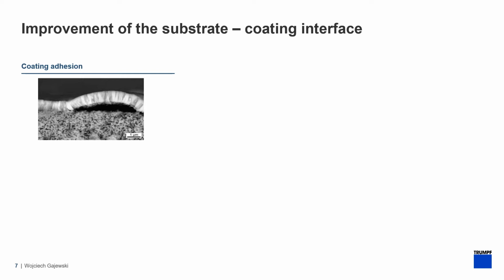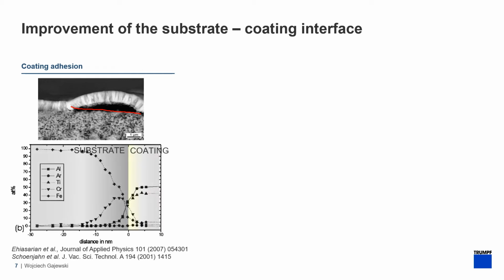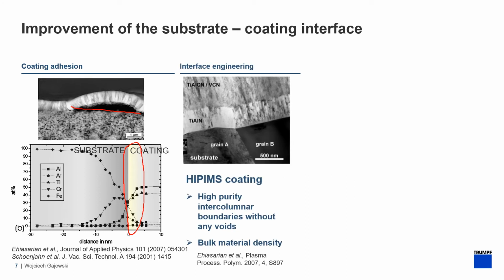Another field where HIPIMS has already proven its advantage is the interface between the substrate and the coating. The coating adhesion problem is one of the biggest nightmares of process engineers. The adhesion problems can be related to the stress in the film, but it can also be tuned by applying an adhesive layer between the substrate and the coating, so a transition layer between them, which will bond the coating to the substrate. By using such technology, it was shown that we can change the interface between the substrate and the coating and get coatings of bulk material density without any voids between the substrate and the coating.